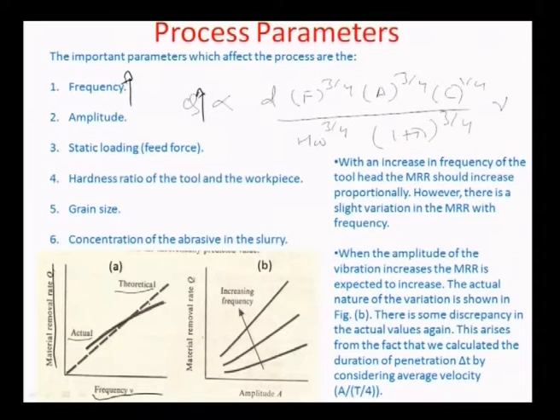So is the case with amplitude. As you may recall, if amplitude increases, A to the power 3/4 is proportional to Q, the MRR, the material removal rate. Therefore any increase in amplitude would also record an increase in the Q value, which is true here. As you see in one of the cases, for a certain frequency, let us say nu1, for an increase in the amplitude, there is a recorded increase in the material removal rate.